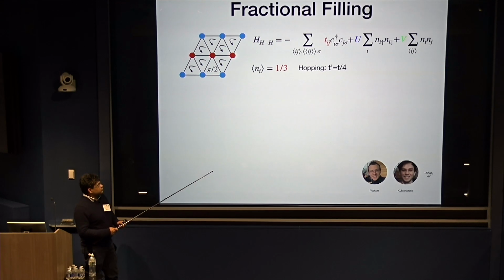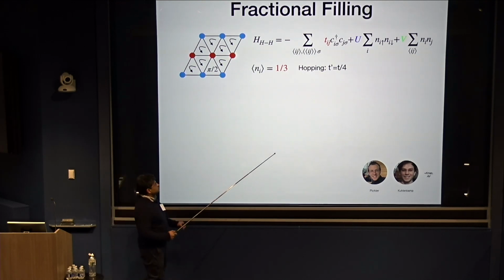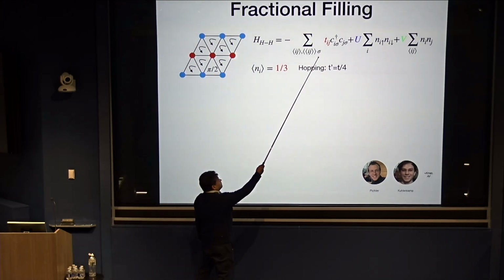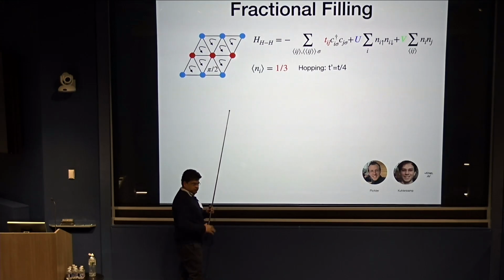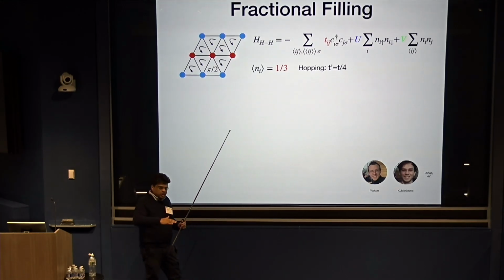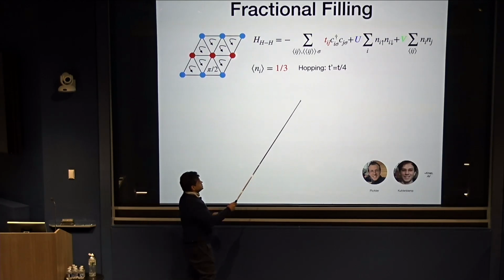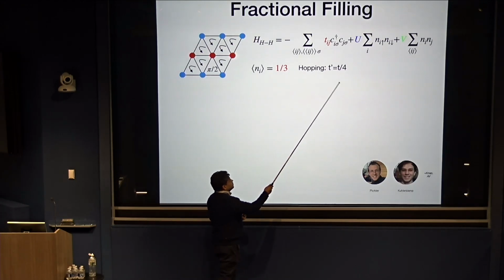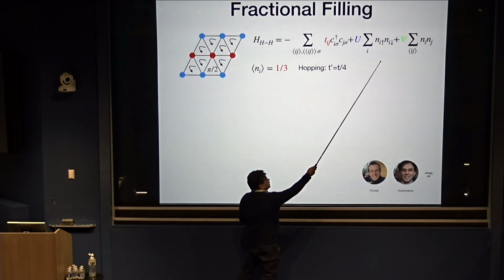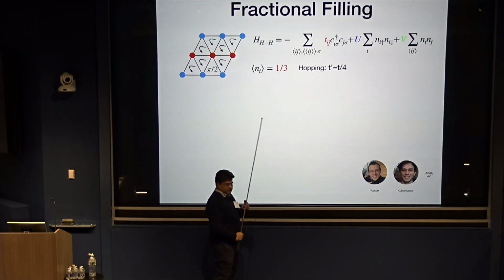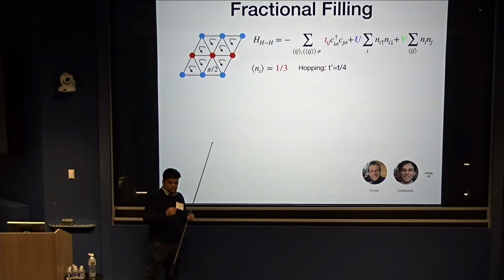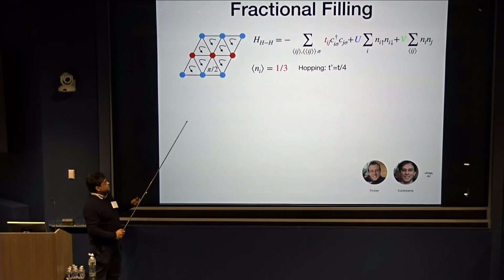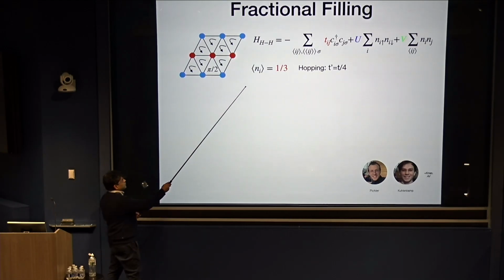And then you have to do a few more things to the model, not major things. One is you want to make the band flat. Now you have fractional filling, you'll usually get a metal, but not if you flatten the band. So they played around with the second neighbor hopping t prime, adjusted to get a flat band. And then because you have very low density of electrons, you need some additional repulsion to make life interesting. So nearest neighbor repulsion, not just on-site. So that's the model, a small variant at filling 1/3.